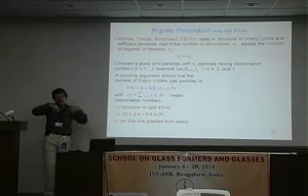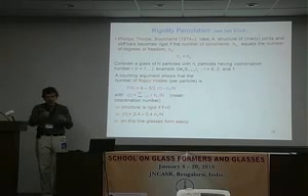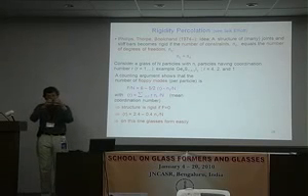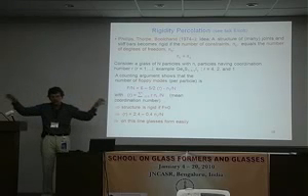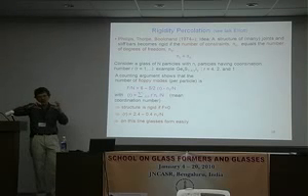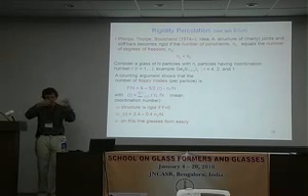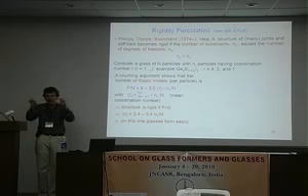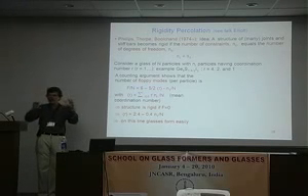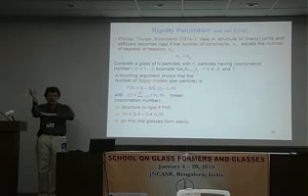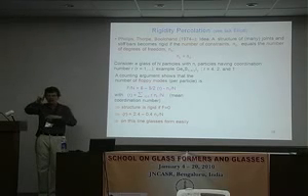If you take an oxide glass where you have strong covalent bonds, so you have this open network structure, you imagine that the atoms are joints and the bonds are just rigid beams. And so you can ask the question, if I have a certain number of beams per joint, is the structure rigid or not? Imagine, for example, if you have two particles, one bond, this gives a rigid structure. You have three particles and two bonds. This is not a rigid structure because you can do this. Okay? If you put in here a third bond, you have a triangle, it's rigid again.